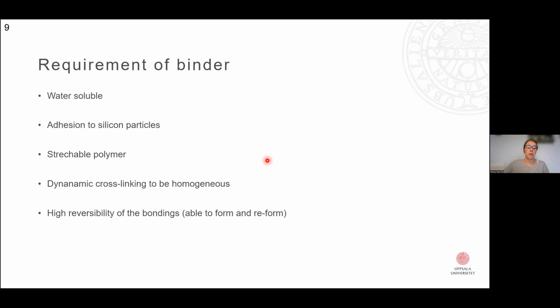If we look at some requirements we have for our binders, firstly it should be water soluble, because we want an environmentally friendly and easy to handle solvent. We need good adhesion to the silicon particles for the interface to be stable. And we can get this, for example, PAA gets this with the linkage between carboxylic acid and hydroxyl group to the silicon oxide layer.